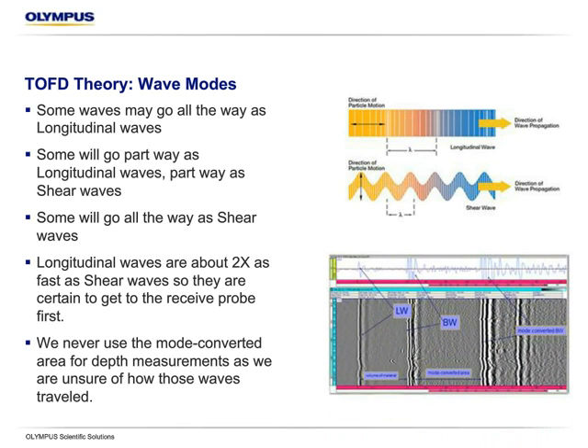So here's our first real look at a typical TOFD display. We have what we call the lateral wave, and we'll go into these a little bit deeper. It travels just under the surface. It's not truly a surface wave, and this is important for a few different factors we'll look at. It's going to arrive first because it's basically almost a straight line from probe to probe. We have a region of what would be our inspected volume, which is typically longitudinal waves. We have what we call a back wall. So if this was a plate or a weld, this would be the reflection and diffracted energy coming from the actual backside of the component or the ID of a pipe.